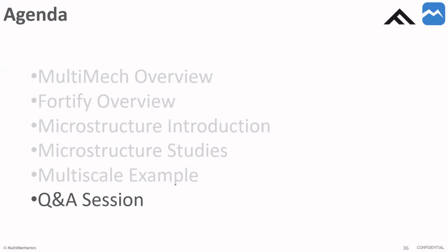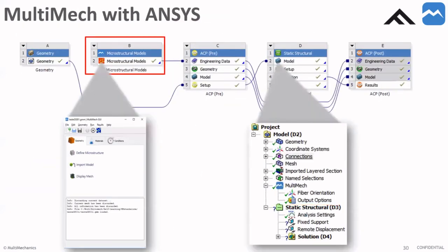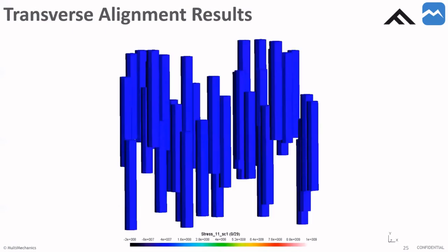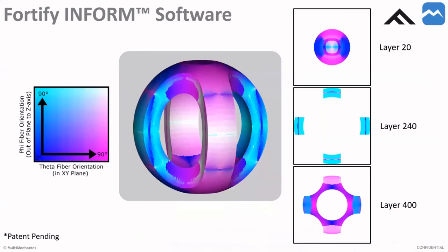Absolutely, and that's what separates us from a lot of our competition. Since we have this magnetic system that is 3 dimensions, we are able to align the fibers in any direction in 3D space. Essentially, you just give it a vector and it'll align to that vector. There's a number of processing difficulties that come with aligning in the Z, fiber length and different considerations. But if Z direction is important, and in a lot of cases it is, then you can adjust the system and adjust your material to allow for that. And that's something that we do a lot, and we're definitely very focused on that.